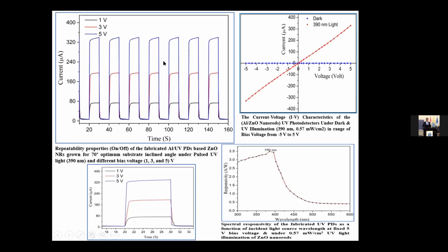This figure shows the repeatability or stability of our UV photodetector sensor properties, on and off, of the fabricated aluminum UV photodetector based on zinc oxide nanorod grown for the optimum substrate inclined angle, which is 70 degree, and the pulsed UV light 390 nanometer at bias voltage from 1 to 5. The UV photodetector device based on the zinc oxide nanorod has the lower dark current, which is about 6.3 microampere, and the high illumination current, which is about 341 microampere.